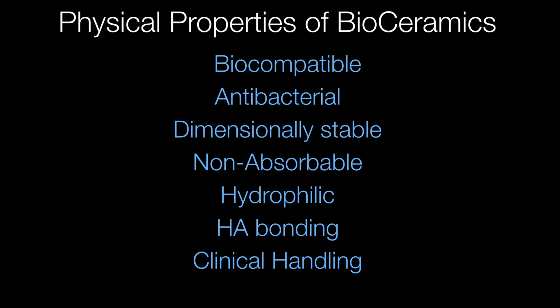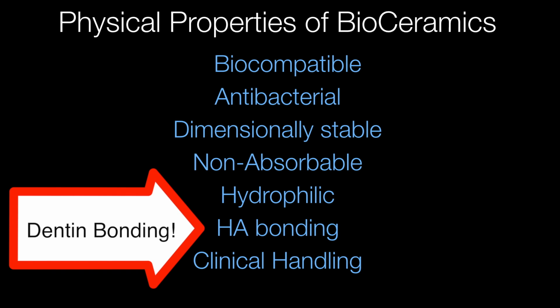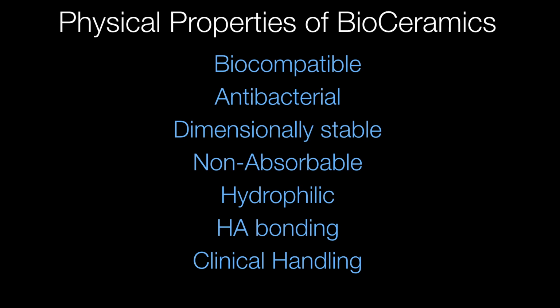It's dimensionally stable, and more importantly, the hydroxyapatite, through cross-linkage, can form a chemical bond with the hydroxyapatite that's in dentin, and you end up getting basically a material that bonds chemically to dentin. So you have a lot of different properties that are really, really helpful. And also, in this particular formulation of this nanoparticulate bioceramic, you have a pre-mixed formulation that does not require any mixing, and you can inject directly into the tooth or put it outside on a pad and place it in the tooth in a very, very simple format.